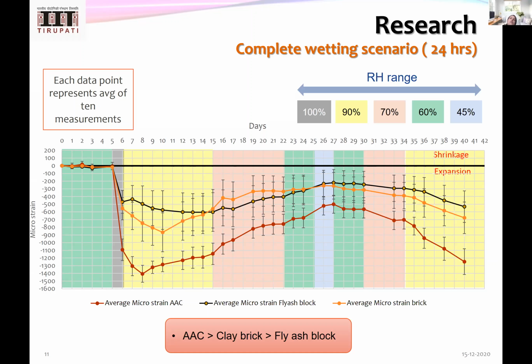An obvious change of climate and other water-applying procedures come because of plastering. Even before doing painting, some people wet the system. So all these processes create a lot of water absorption in the brick, which creates a large amount of expansion. And the relative expansion between the plaster and the brick will be comparably different. So that creates cracks in the system, which is restrained. That's the only reason.